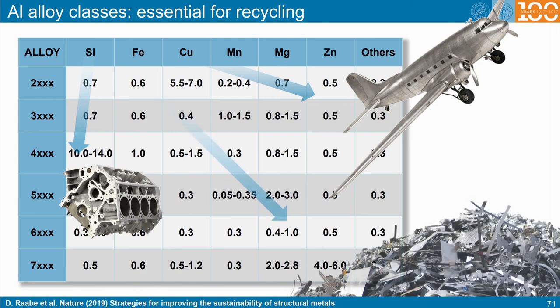A similar situation applies for the 2000 series alloys with high copper content. This element lends the material very high strength, but it is undesired in most other aluminium alloys. Iron is another element that enters through the scrap and through the recycling of cast alloys, but it is undesired in most wrought alloys, such as the 5000 and 6000 series materials, as it promotes formation of brittle intermetallics.